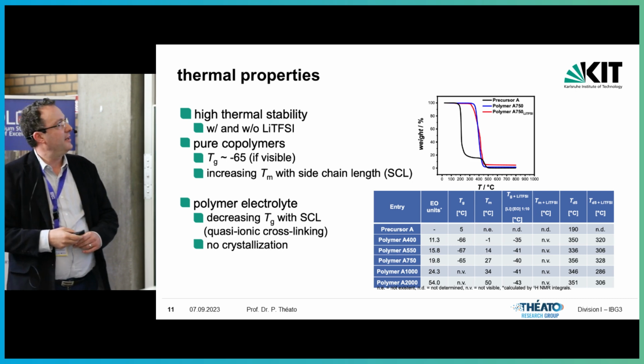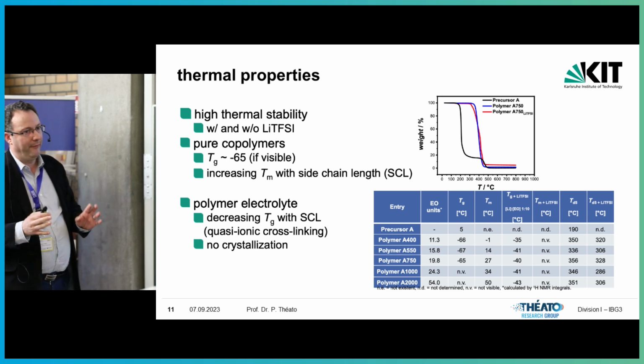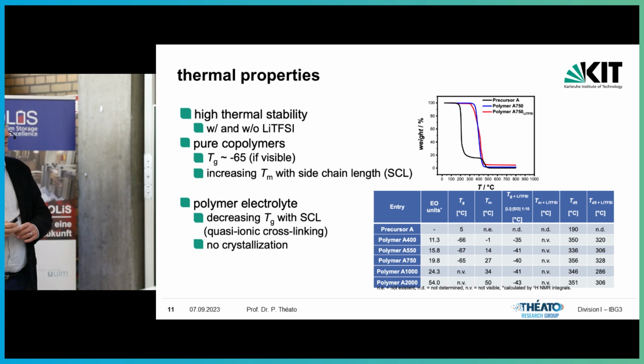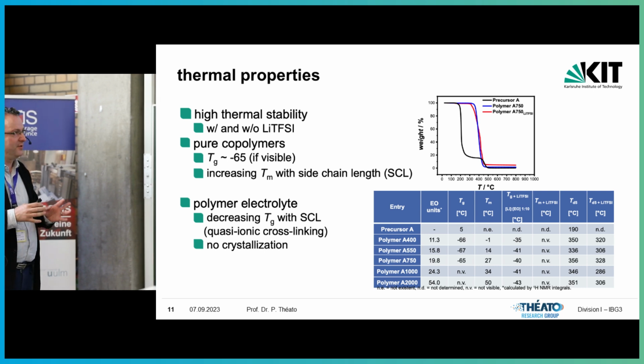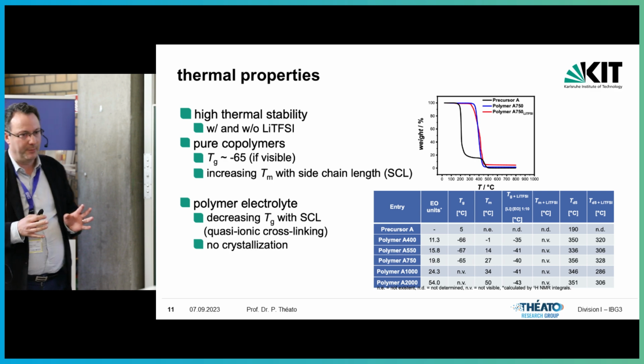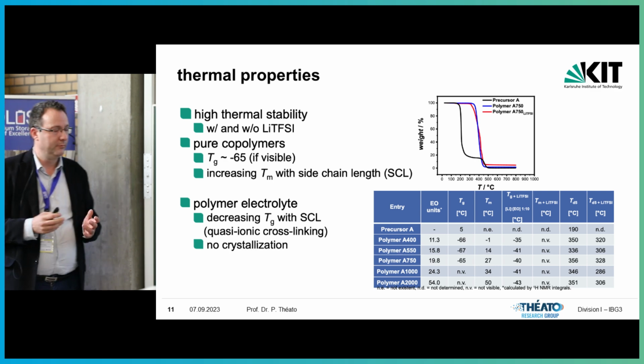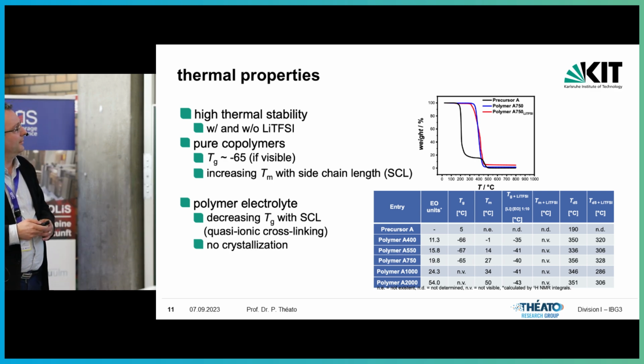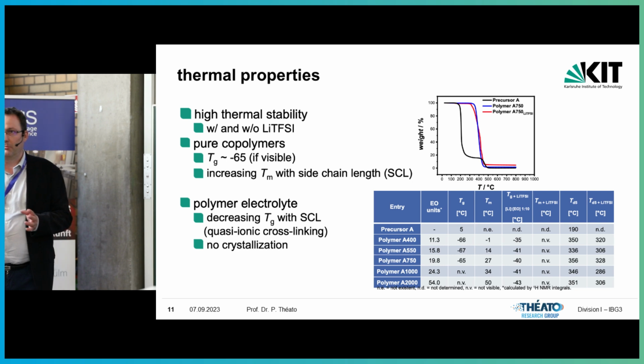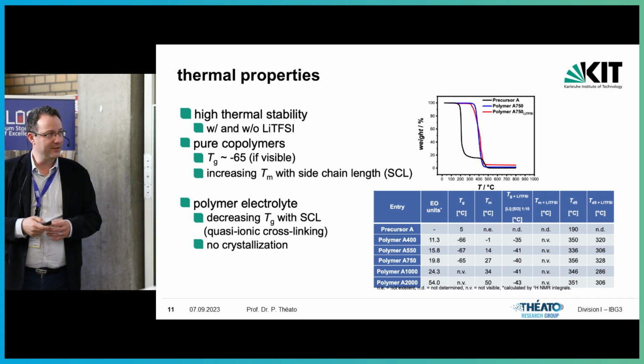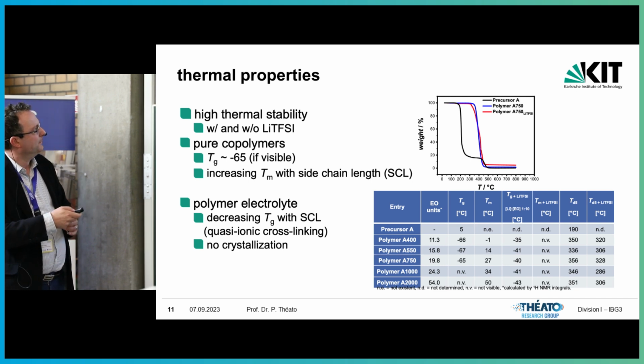You can see the TGA data here for the systems. Above 300 is sort of where degradation slowly starts, but they're pretty stable, very good. The glass transition temperature, if you can detect it, sometimes a bit difficult, is about minus 65 degrees centigrade for pure systems in there. We do see a melting point of the side chain, in particular for the longer side chains. So the longer the chain, the more likely a crystallization is. So there is a certain cutoff.